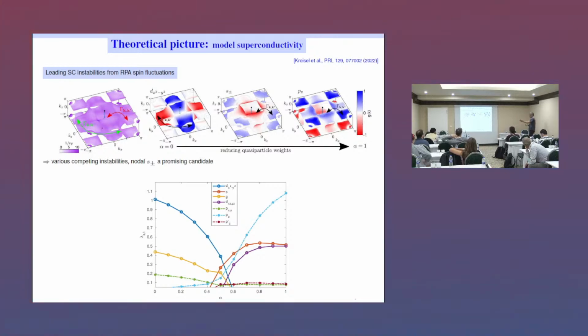And triplet-like, that would go along with Ariando's finding, that indeed there could be some triplet instability. That could connect to this flat band, which maybe carries more ferromagnetic spin tendencies, and that is maybe closer to a triplet instability. However, we think that with an RPA, it's hard to decide. Also, triplet usually needs more vertex corrections, which are of course not included in RPA. So in this work, we still favor the S plus minus, which would also be nodal in our case.